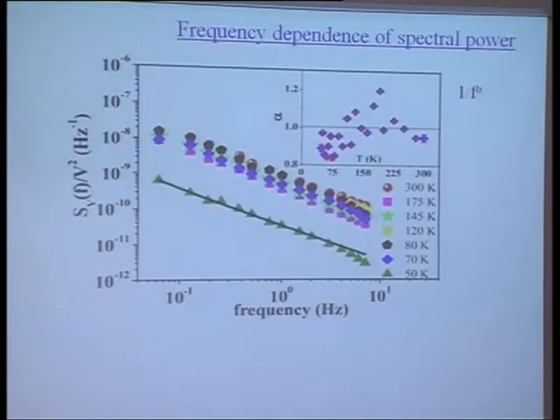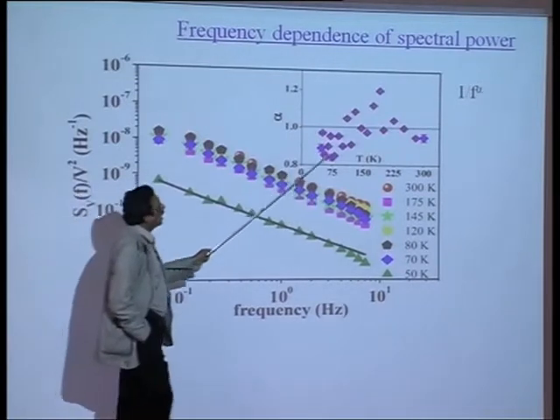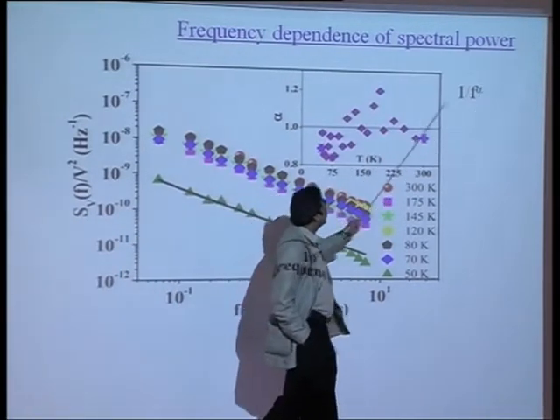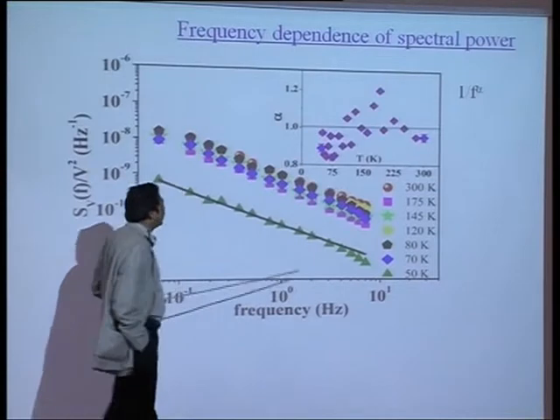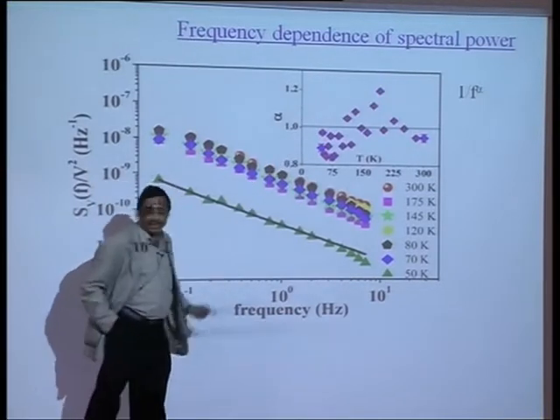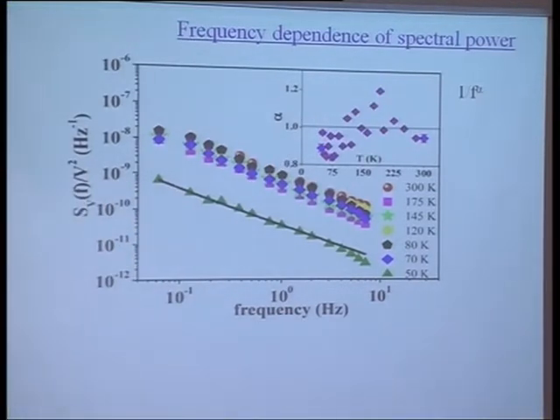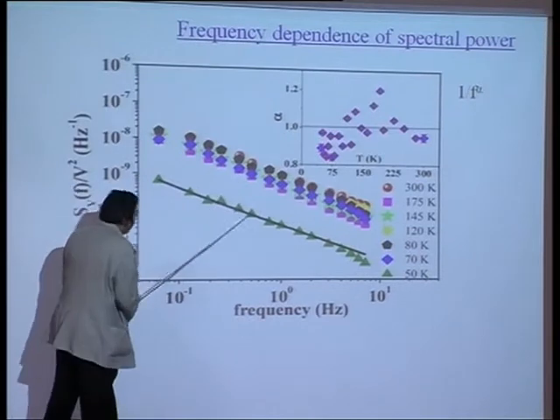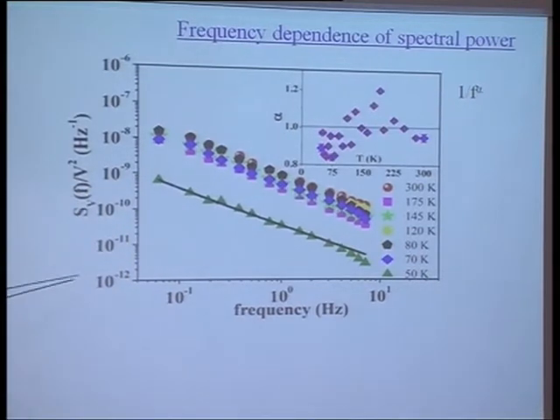Okay, and this is the noise that you measure, the 1/f noise and all that. And you can see this is the alpha over here. The alpha has a slight temperature dependence, but it is typically within the ballpark of 1 plus minus 0.2. And you can see that at some temperature like 50K, the noise has started coming down. And is this noise large or small?